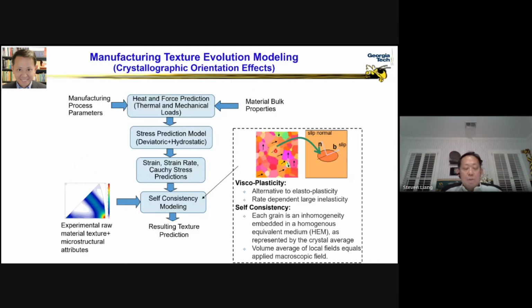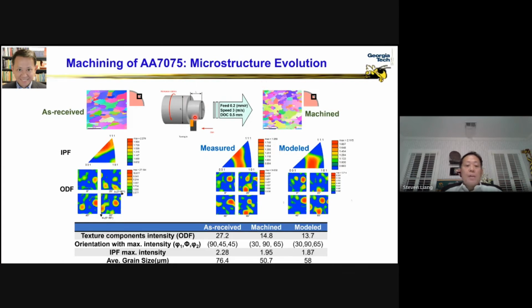And with the analysis at the microscopic microstructure level, which we call viscoplastic self-consistency analysis, we're able to predict what exactly is going to happen to the workpiece when the machining operation takes place. For example, on the left-hand side, we have a set of pole figures taken on the uncut part as a raw material. Then when the material is cut into the final product, its microstructure crystallographic orientation is shown on the right-hand side. That is modeled by our analytical predictions in comparison to experimental measurements on the left, in terms of the inverse pole figure in the middle row, as well as the orientation distribution function. The orientation distribution function basically represents the features of the texture before and after cut.